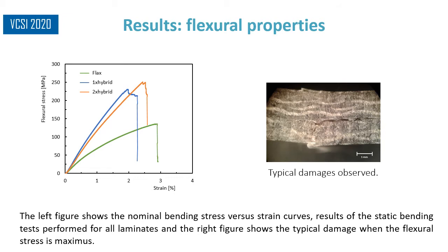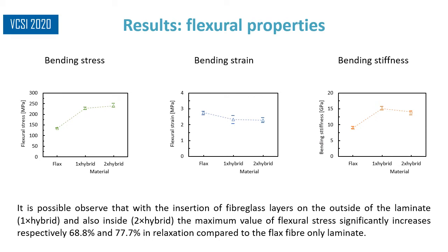When the flexural stress is maximum, fibre breakage occurs, as can be seen in the figure. The typical damage at this point. It is possible to observe that with the insertion of fiberglass layers on the outside of the laminate, 1x hybrid, and also inside, 2x hybrid, the maximum value of flexural stress significantly increases.